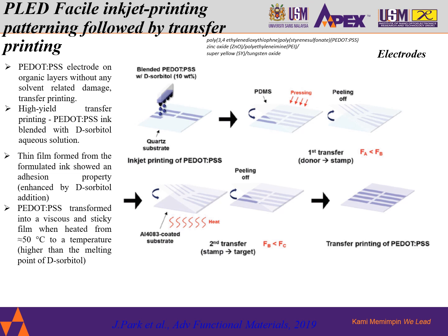Fabrication of PLED using facile inkjet printing patterning followed by transfer printing. Poly(3,4-ethylenedioxythiophene) polystyrene sulfonate (PEDOT:PSS) and polydimethylsiloxane (PDMS) are typical conductive polymers and transparent elastomers, respectively, which are widely used in the field of stretchable electronics. For example, the pattern of highly conductive PEDOT:PSS electrode on top of the organic layers without any solvent-related damage by transfer printing. Then with the pressing, followed by the peeling off, and the high transfer of PEDOT:PSS ink blended with 10 weight percentage of D-sorbitol functions as an adhesion property.